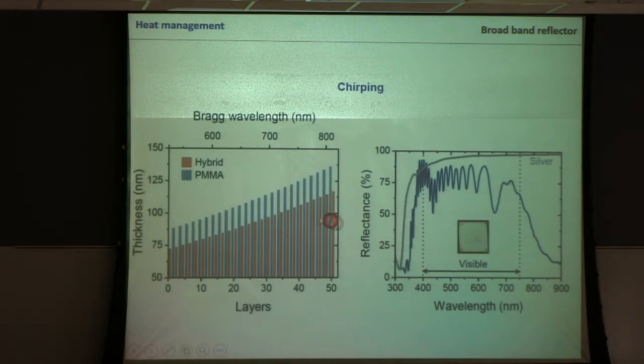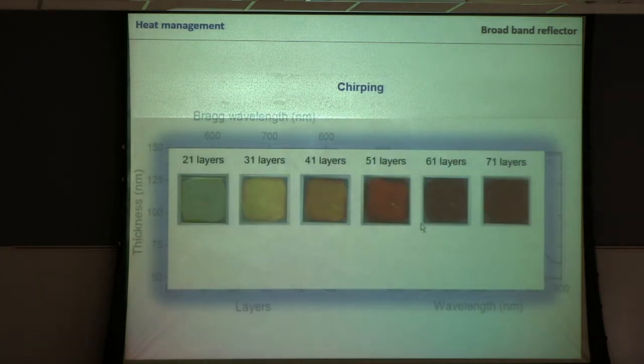So here is actually a mirror that was indeed produced with these 51 or 52 layers. And you see we can get reflection in this case over the whole visible. And actually the film really visibly, the photograph doesn't do it merit, looks like silver, despite it's only made of plastic. And you see that also in transmission.